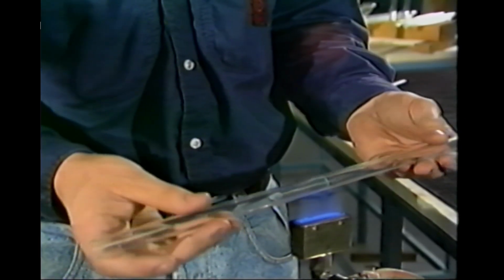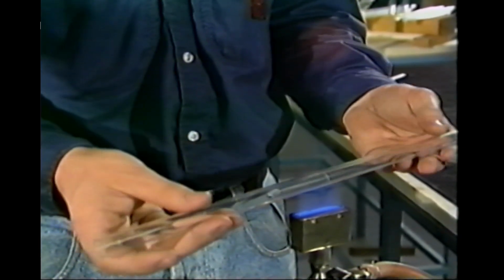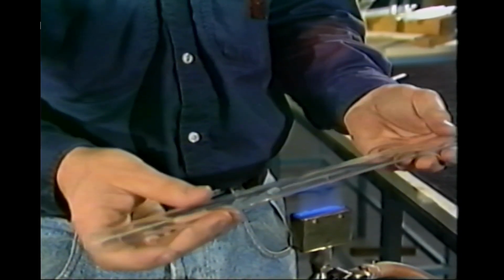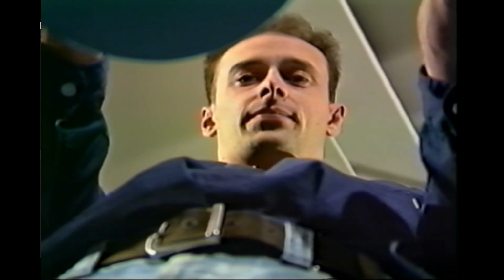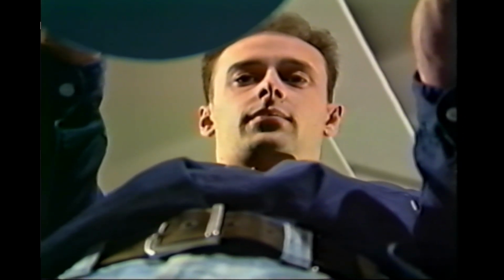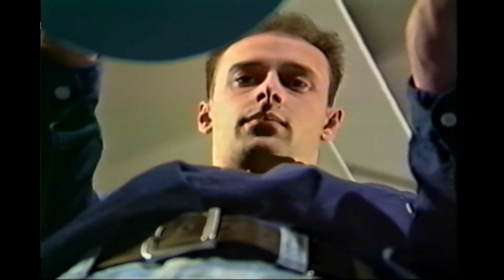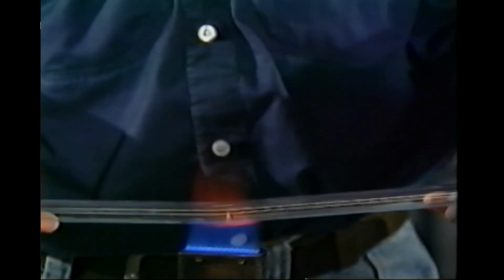During melting, keep the tube horizontal and the pencil mark central in the flame to achieve equally melted areas either side of the pencil mark. The glass must be melted for much longer than for the right angle bend. When the melted glass glows orange-red, cease rotation, bringing the pencil mark to the top.